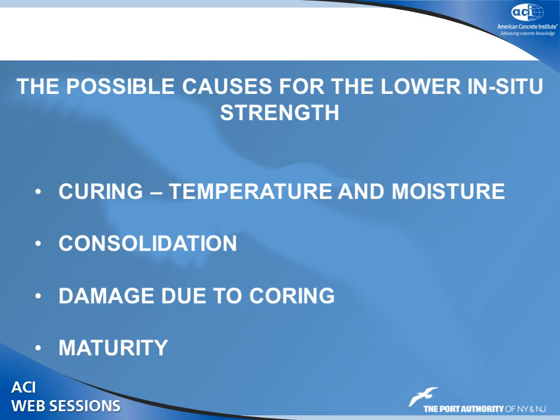We think part of the reason for having different strength in place is, number one, curing. We cure cylinders in accordance with C31. When was the last time we cured the concrete in place in accordance with C31? Never. And, as an owner, we really don't take too much comfort in knowing that the cylinders are good, but the in-place concrete stinks.